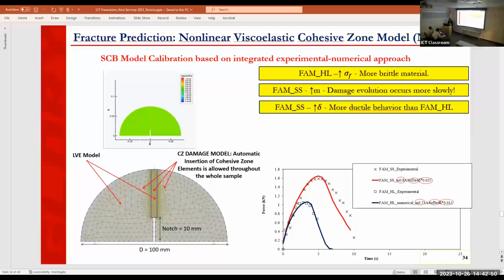And we can get nice videos like this. We can observe that as the sample is loaded, we have compressive stress on the top, and tensile stress developed at the crack tip until, at a certain level, the stress is too high and the crack starts to propagate. And that's what you're going to observe here. The tensile stress is getting higher, until there is a point that the sample does not sustain anymore, and the crack starts to propagate.